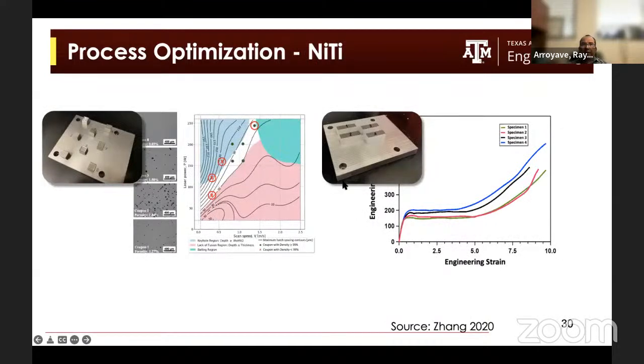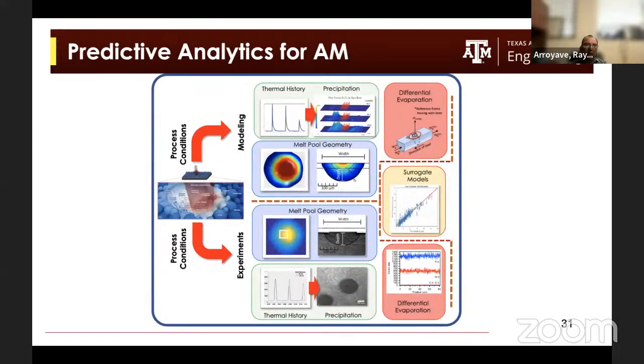And here we have an example of nickel titanium where we have found the sweet spot using the framework that I presented in the previous slide. We have found that the sweet spot doesn't have porosity, and we have shown how we can fabricate these bars of this material that have interesting and repeatable stress strain responses.